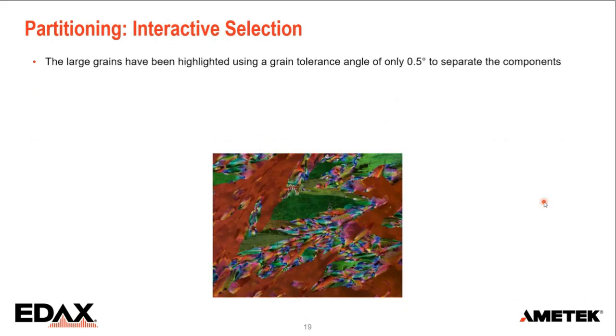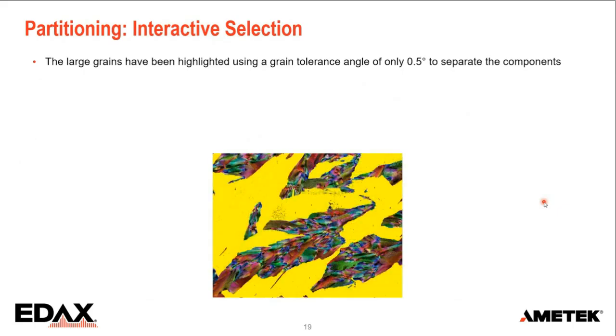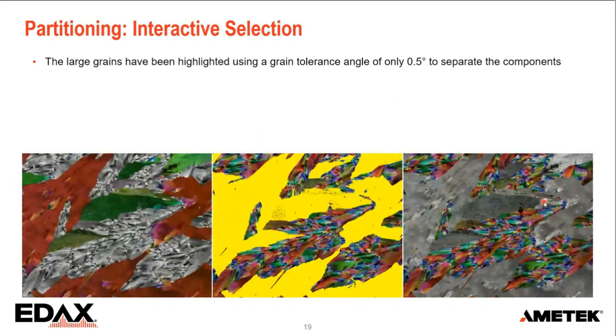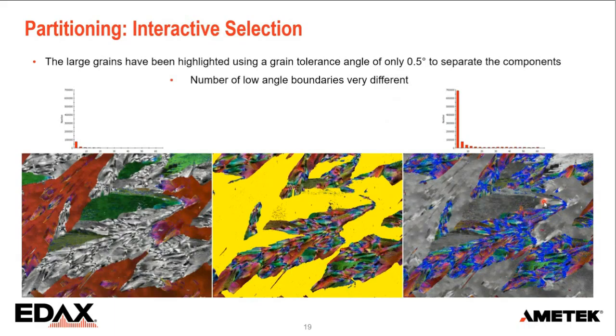Now, I've tried to do this from a chart. That didn't really work. I didn't really get the grains that I wanted. So instead, I can just manually click in the grains that I want to select. In this case, I just wanted the really big ones. And then I can use that to tell them apart. So just pull the data set apart, make different partitions, and then in each partition I can make a chart like this one. This is grain boundary misorientation distribution. And here we have a lot of low angle boundaries, and here are a few high angle boundaries.